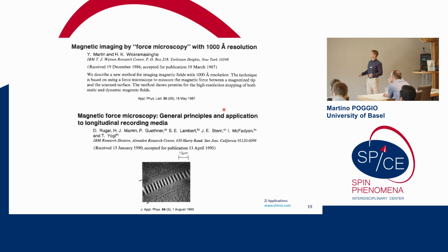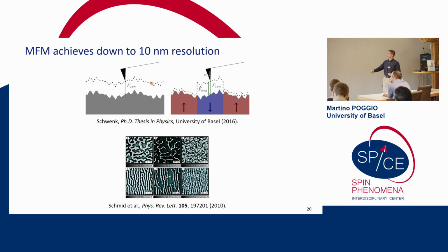This is a very old technique that was born in the 80s after all the revolution in scanning probe microscopy started, after they invented STM and atomic force microscopy. And the idea is just that you take a mechanical cantilever, so some kind of compliant object, and you coat it with some magnetic material such that the tip is magnetic, and you scan it above some magnetic material, and there will be a force on that tip that depends essentially on the stray fields produced by the sample underneath.